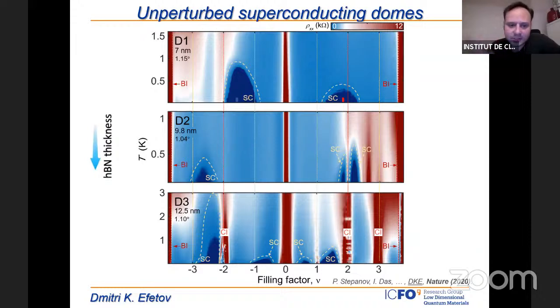We have made several devices which all have varying distances to the graphite gate. The lowest device here is dead-on magic angle, and it has the thickest hBN. In this device, what is really important is that we get those red regions, which are the resistive insulating regions at integer filling. Here at -2 electrons per unit cell, at +2, at +3, and even at 1, we get correlated insulators, and the correlated insulators are not interrupted by the superconductors.